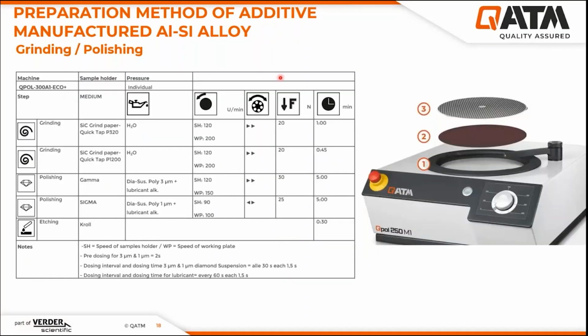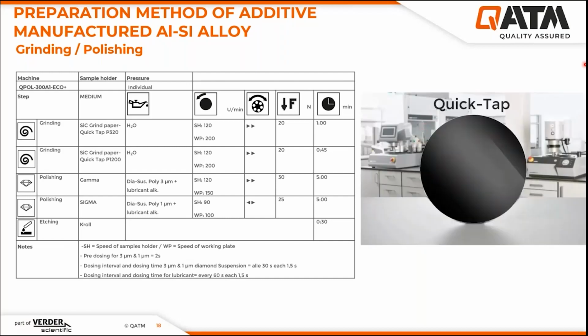Now I will show you the preparation method of additive manufactured aluminum silicon alloy. Here we use SiC grinding paper, but with no elasticity or lower elasticity, because here on the right-hand side you can see the working plate, magnet foil, and on the magnet foil you can have the grinding disc or adapter disc. Here, the adapter disc between the SiC paper and working plate is a Quick Tap. Quick Tap is an adapter disc with a metallic back, and you can also use the normal SiC grinding paper on it with low elasticity. Here we use P320 and P1200 for grinding, and after that 3 micron and 1 micron for polishing. For etching, we use the Kroll etchant for 30 seconds.